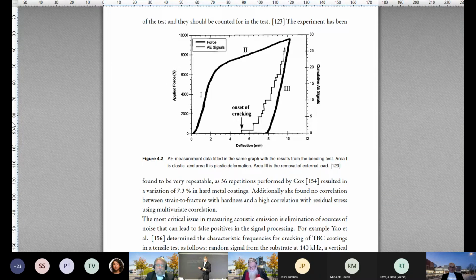So at 0.0, the coating would look like this. You would start to bend it, which is a tensile stress, from this side in this case. And once you make it to the onset of cracking, as recorded by the AE, there would be micro cracks. In my thinking, that would be individual splats cracking, perhaps some delamination within the coating. So these would occur continuously as long as we keep pulling the coating apart, essentially.